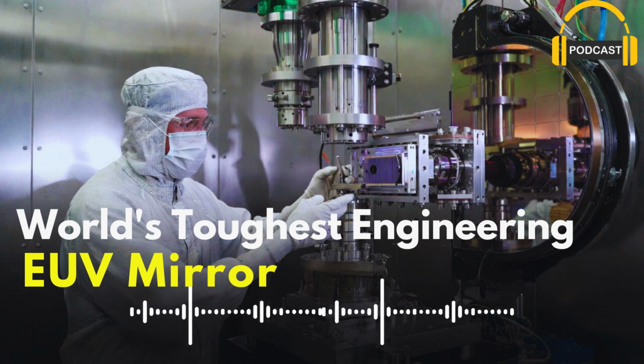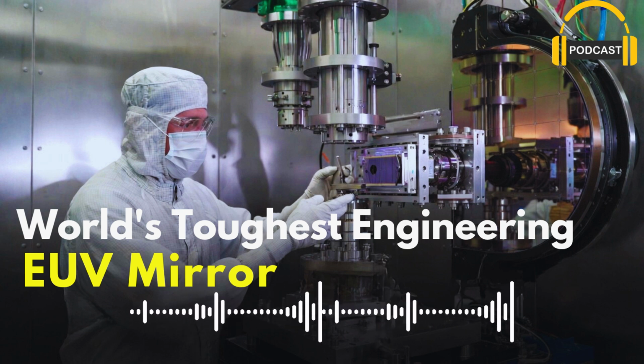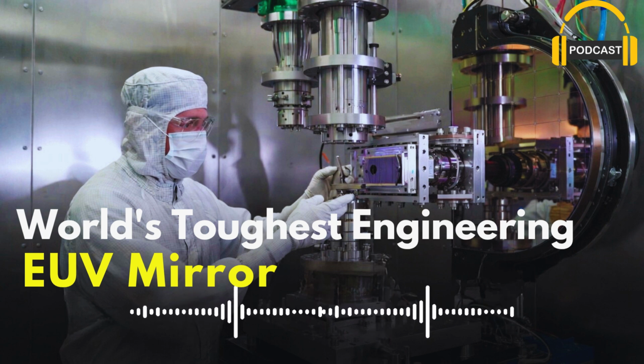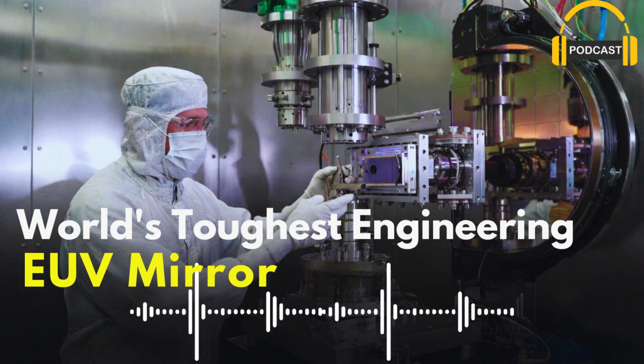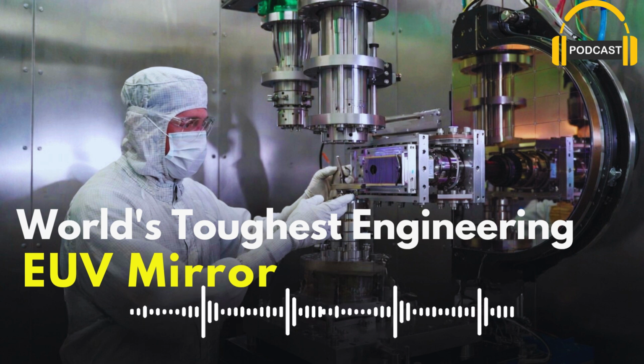By the mid-2010s, inline EUV power reached 100 plus watts, then 200 plus watts, and eventually over 250 watts in production tools like the NXE 3400 and NXE 3600 series. With enough light, plus Zeiss mirrors, plus improved stages and metrology, throughput finally crossed the threshold. By 2018-2019, major foundries like TSMC and Samsung started inserting EUV into real production lines for 7 nanometers, then 5 nanometers, 3 nanometers, and now 2 nanometers class nodes.